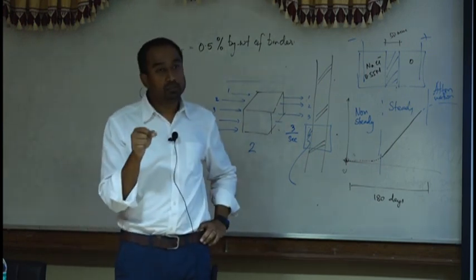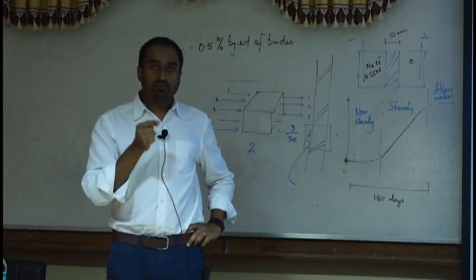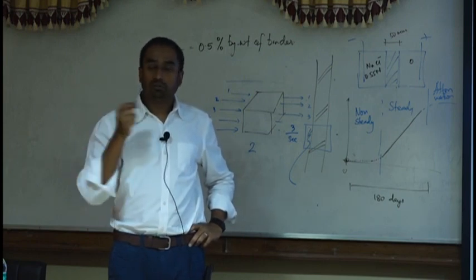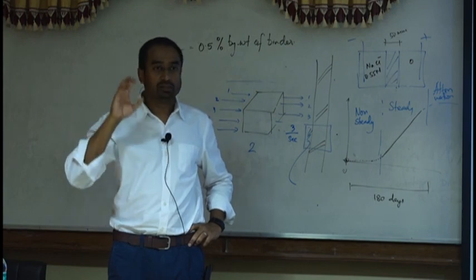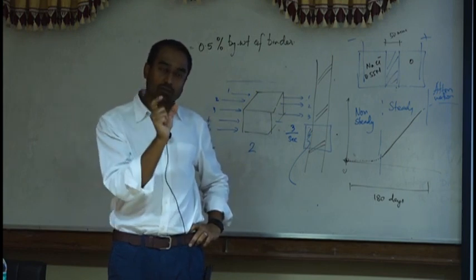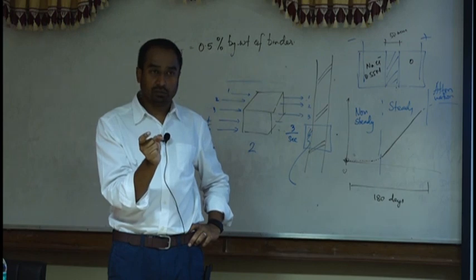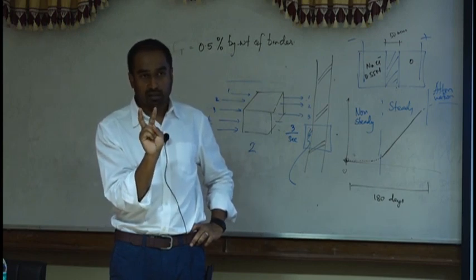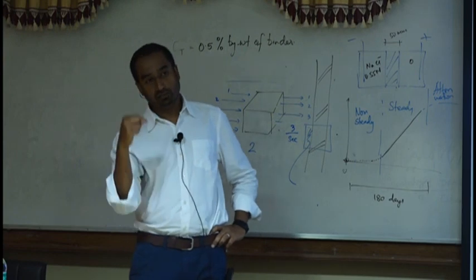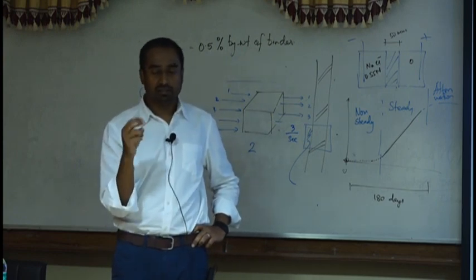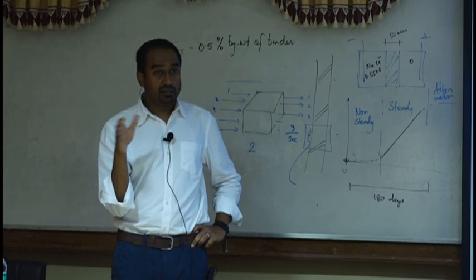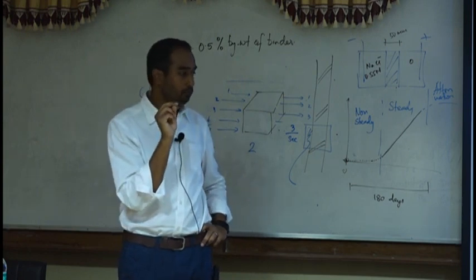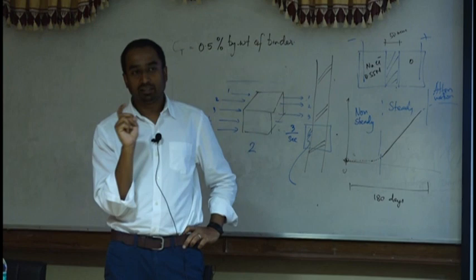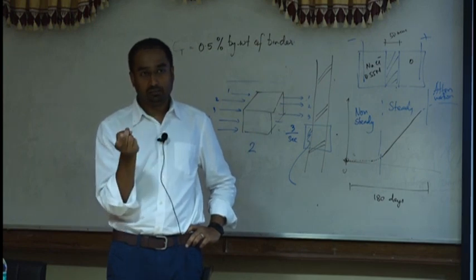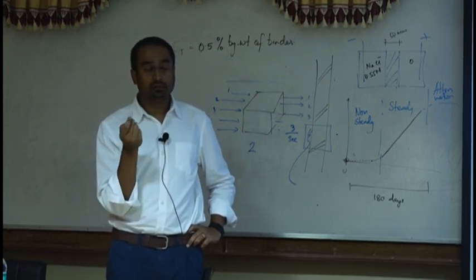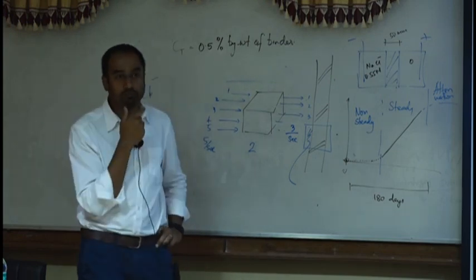I have a reason for saying might be, because threshold is very much connected by the work Rasheeduzzafar and a few others did years ago. They connected chloride threshold to the hydroxide concentration. And they were saying that chloride should be referred to as chloride divided by hydroxide concentration, basically pH. And they had good reasons to say that. It's a very consistent result. Which means Portland cement has higher pH. So Portland cement highly likely will have a higher threshold.